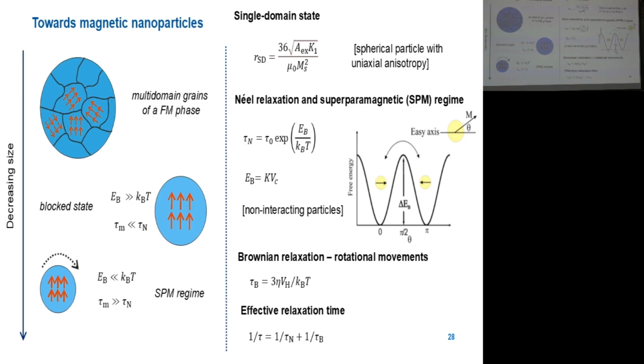If you observe the particle long enough, maybe you will see after a long time some relaxation. You will see this transition to the opposite direction of the easy axis. So you will see some reversal. So the concept of superparamagnetism or of this state is also dependent on the time scale of your observation. So it is relative. Superparamagnetism is nothing absolute. It is dependent on your time window.